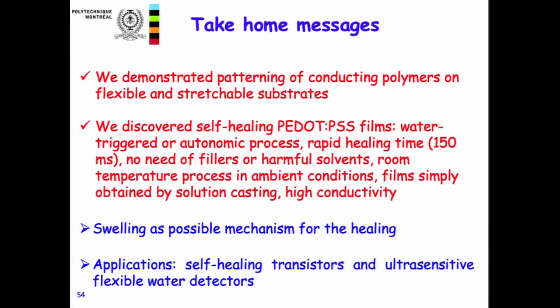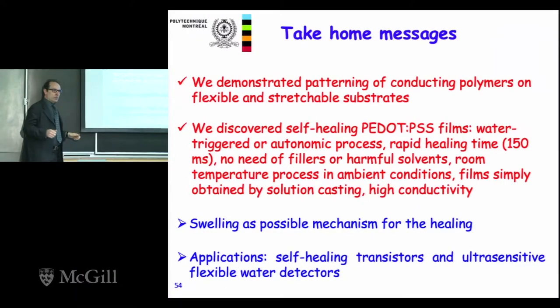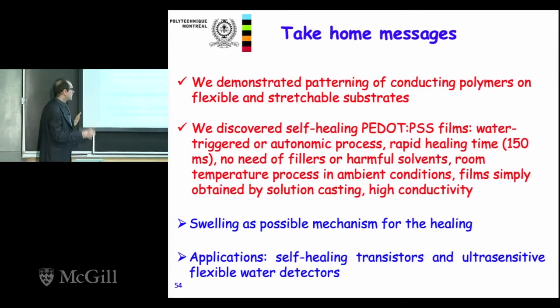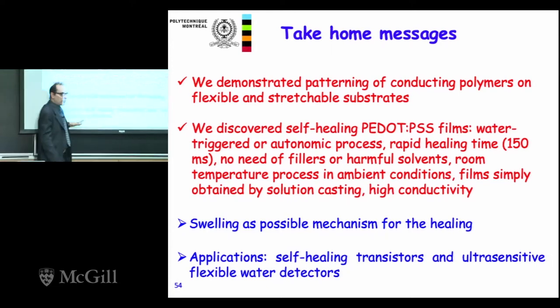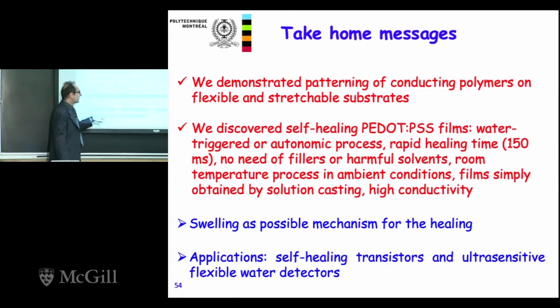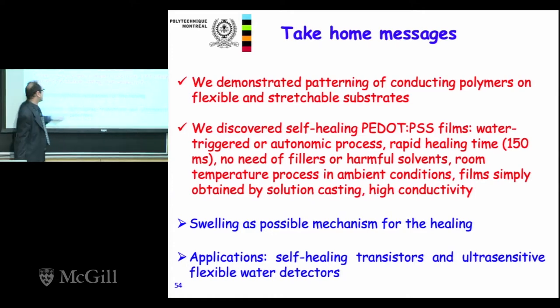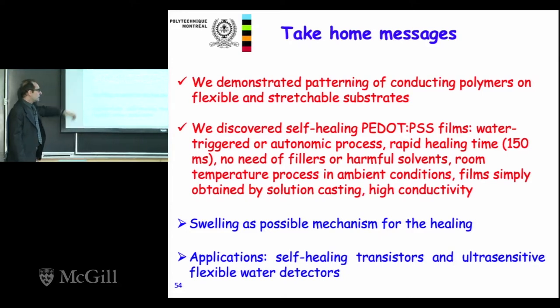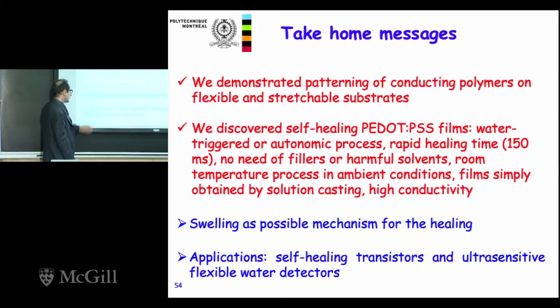But the very important thing for me is the discovery of the self-healing ability of PEDOT:PSS. And I want to point out that the good thing of this process is that it's water-triggered, so triggered by a very simple chemical, or autonomic. So we don't need any complex solvent, heating, or nanoparticles. It's a very simple process. And also the way we make the samples is quite simple. And what is also very important is that this material has a high conductivity for a healable material. And then, of course, we are still working on a possible mechanism. And, of course, we are trying to find applications for these materials and devices, especially for flexible electronics.